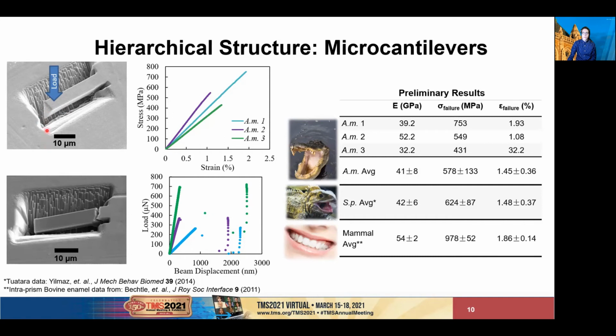Then we brought them to the nanoindenter, which lets us measure the displacement and load applied near the tip of the cantilever. You can see the beams deform elastically before sudden failure, where the displacement would jump by a few microns. We then converted the force displacement data into stress and strain, accounting for the triangular cross-section of the cantilever, and the results are presented here in this table. We got an average modulus of 41 gigapascals and a bending strength of about 580 megapascals.